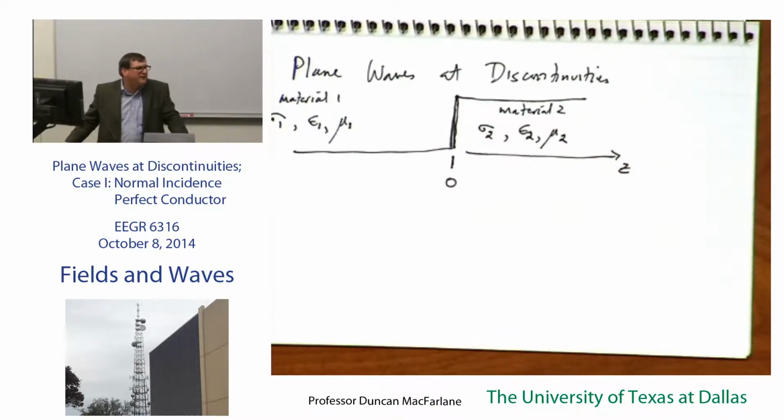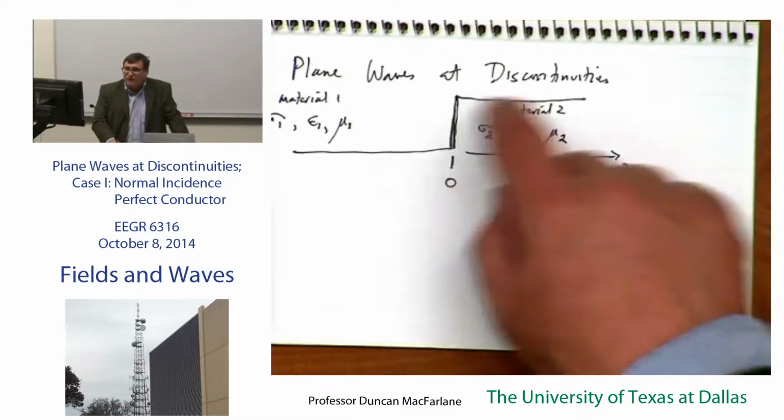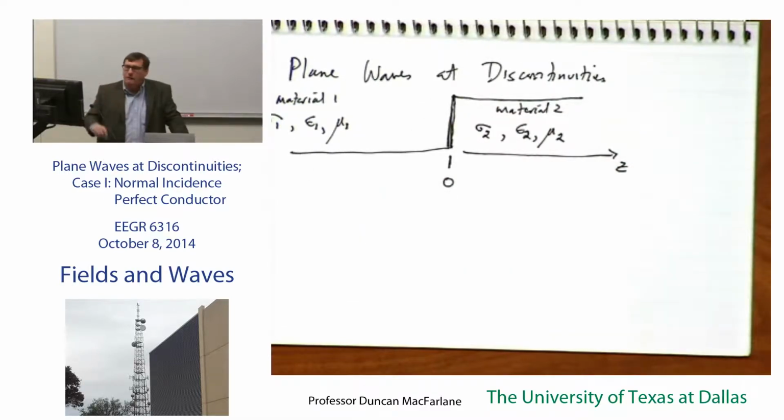Okay, so thinking a little bit about the practicalities of what this step function is just kind of tells you what problem we're solving. If I have a metal surface and I'm trying to build a metal mirror for the optical world, I've got to polish that very, very, very fine. If I'm trying to take a copper pipe and use it as an electrode inside of a CO2 laser, which works at 10 microns, I can get away with any old metal polish to make it smooth. As long as it's smooth and shiny, roughly in the visible, it'll be as flat as you can be at 10 microns, 10 times the visible.